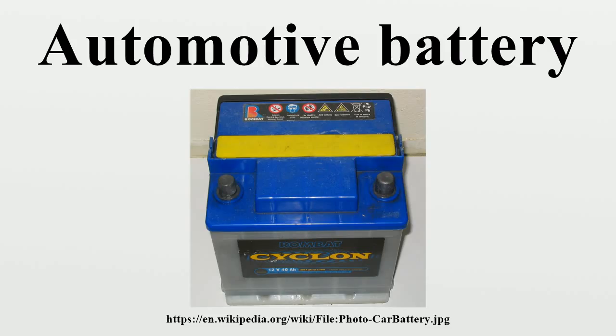When first installing a newly purchased battery, a top-up charge at a low rate with an external battery charger will maximize battery life and minimize the load on the vehicle charging system. Failure. Common battery faults include shorted cell due to failure of the separator between the positive and negative plates, shorted cell or cells due to buildup of shed plate material below the plates of the cell, broken internal connections due to corrosion, broken plates due to vibration and corrosion, low electrolyte level, cracked or broken case, broken terminals, sulfation after prolonged disuse in a low or zero charged state, frequent and continuous overcharge.